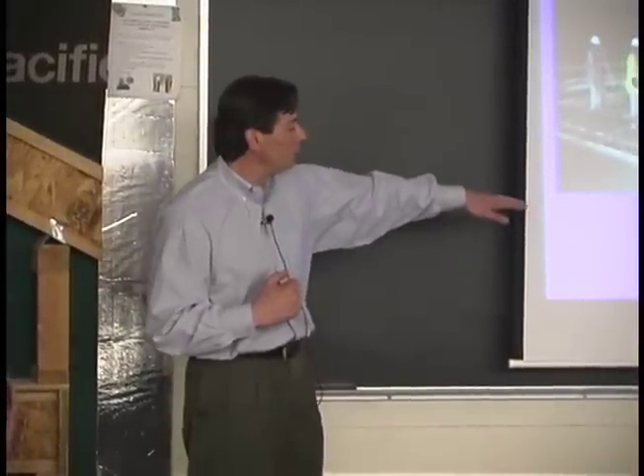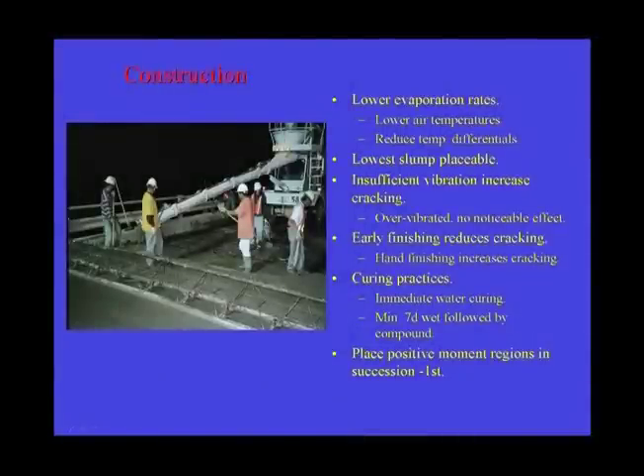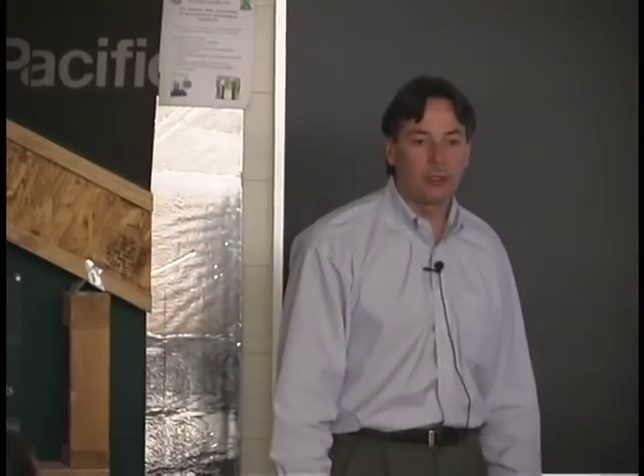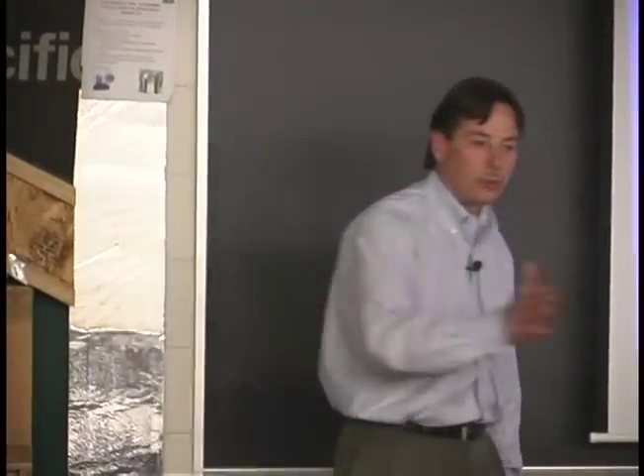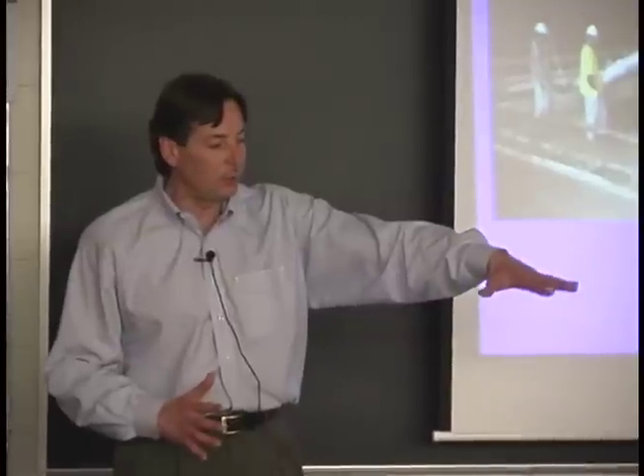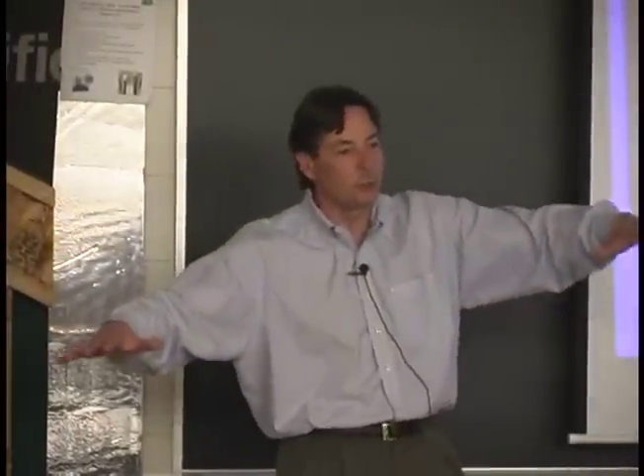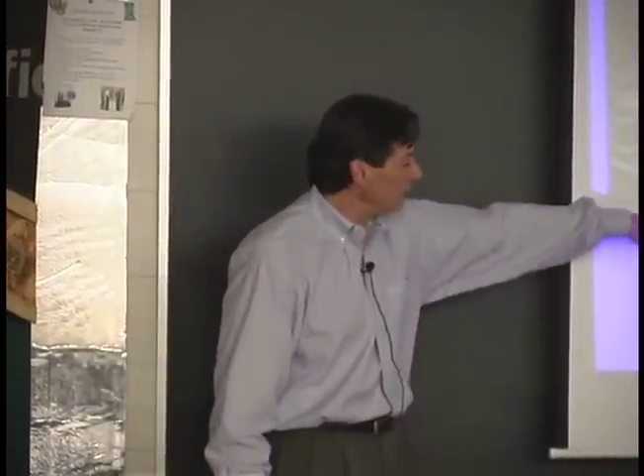So when you build multiple span bridges, you have to place all the positive moment regions first. You have to place all those regions over top of the columns first, and then you come back the next day and you do the negative moment regions, because of that weight loading. If you were to do the one continuous pour straight through, this extra weight on this 3rd or 4th segment would be cracking this concrete all the way back here just because of the extra weight tilting the bridge. And this concrete back here is not hard enough to support its own weight yet. So there's a little bit different construction practice when you're doing excessively long bridges on placements.